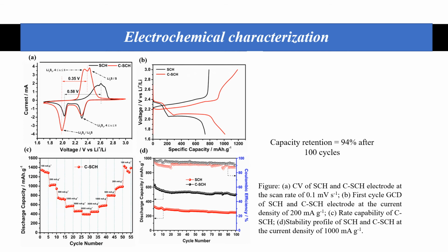Later, we performed the rate performance on the carbon coated sample, which is shown in figure C, where we can see it is well behaving at each current density, and once we reverse the current rate after going to higher current rate, it is retracing the previous capacity, which shows the excellent performance of the material. Later, to examine the cycle life, we performed the long-term cyclic stability for 100 cycles at 1000 milliampere per gram, where we observed the capacity retention of 94% for the carbon coated sample, which again really reveals the advantage of the candle soot overlayer over the electrode.